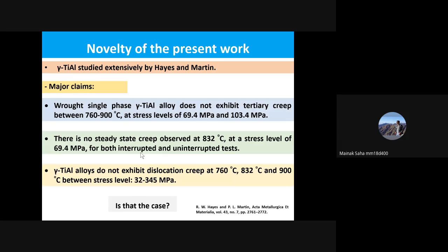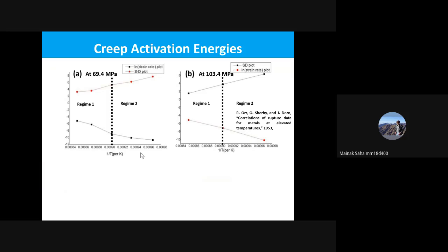In order to explain this, firstly, the creep activation energies have been determined. These are the two plots. First of all, this is the strain rate, epsilon dot, which is plotted as a function of 1 by T, where temperature is in Kelvin, and the other one is the Sherby-Dorn plot.